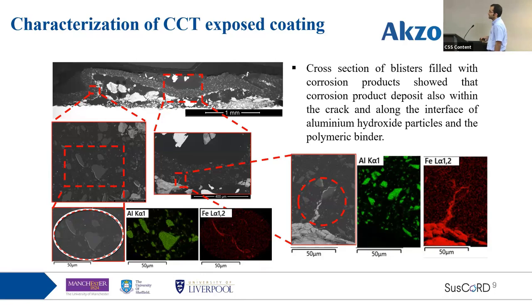But we also have other cases where corrosion product is detected at the interface, but there are no evident cracks there. So the question to be answered is how these corrosion products have been deposited there. Is there an interconnected network that allows transport of corrosion products, or are there pathways within the organic coating polymer itself that allow corrosion products to move there and get deposited? And what has happened to this interface?